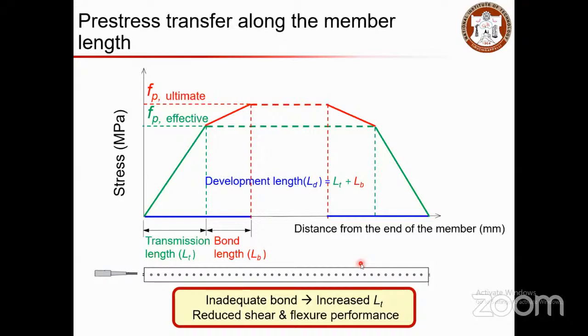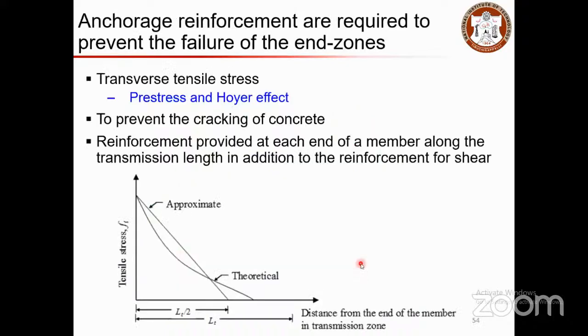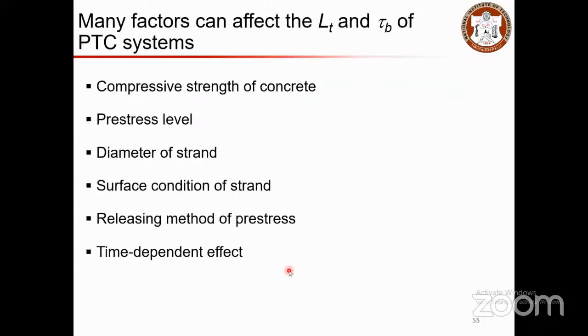So inadequate bond will result in increased transmission length, and that will reduce the shear and flexural performance in the critical regions. Especially in the ends, the anchorage reinforcements are crucial. That depends on the transmission length of your member. So the major factors that influence the transmission length are the compressive strength of concrete, stress level, diameter of strand, surface condition of strand, releasing methods, and time-dependent effects.